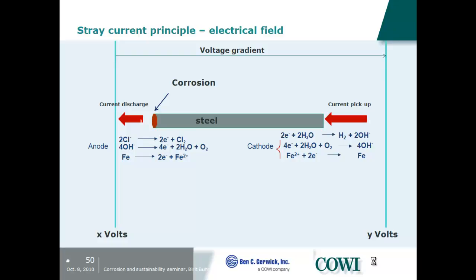The principle on these stray currents, if you have a voltage gradient, is that you have current which will be running perpendicular to these voltage lines. Where the current enters your steel, think about this as a steel in an electrolyte. It could be concrete, it could be water, it could be anything, but something that can lead currents. Current will be picked up in one end. A steel has a very, very low resistance. It would, in many cases, if that resistance path is lower than the resistance path you have outside,